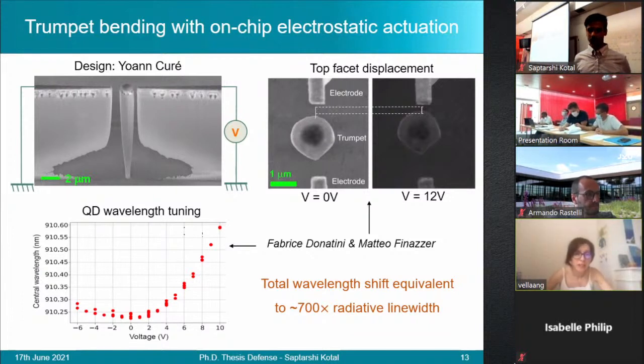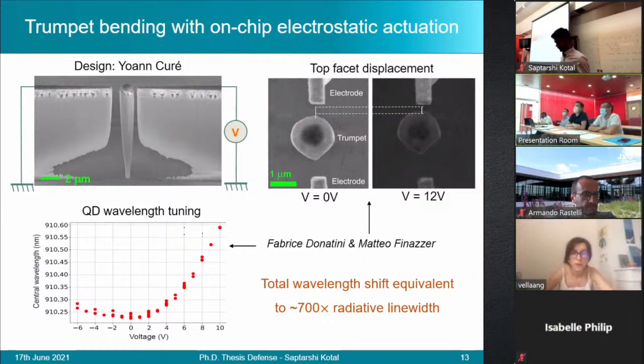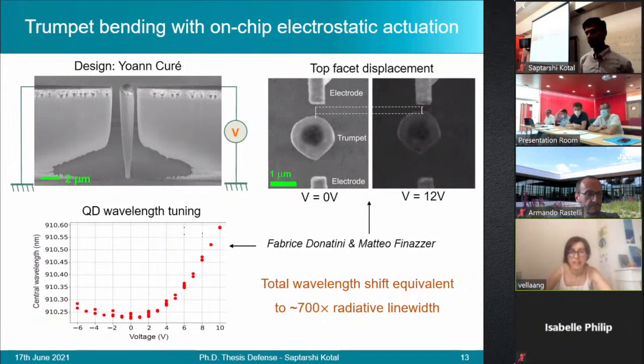Because if you look at the results you obtain about the tuning of the wavelength, when you applied a negative voltage, as you can see in this plot you have on slide 13, when the voltage is positive, you have a redshift. And when it is negative, you also have a redshift, which for me is strange. It is smaller, this redshift for negative voltages, but it is still in the same direction. So why? Because if you change the polarization, you should bend the trumpet in the opposite direction, not in the same. How can you explain that you always observe a red shift for this one or the blue shift for the other quantum dot?